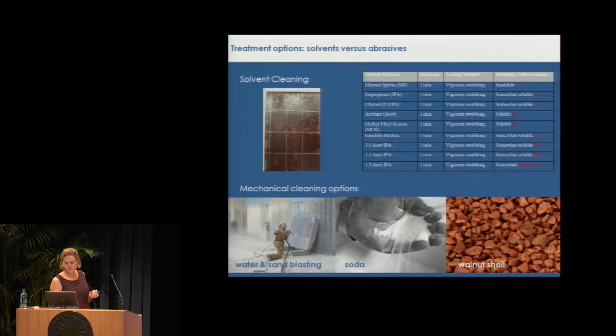So we tried to do some solvent tests, and they were kind of disappointing. What we did is we only used the marine spar varnish, because that was the latest varnish that was put on the sculpture. So we coated some test panels of steel, mild steel, low carbon steel, with 2 layers of the marine spar varnish, and we let it dry and then put it in a UV chamber for a couple of days. And then we decided to do little swabbing tests with solvents. And the result was, as I said, not so good. Only acetone, so fast evaporating solvents or very toxic solvents, could remove the coating.